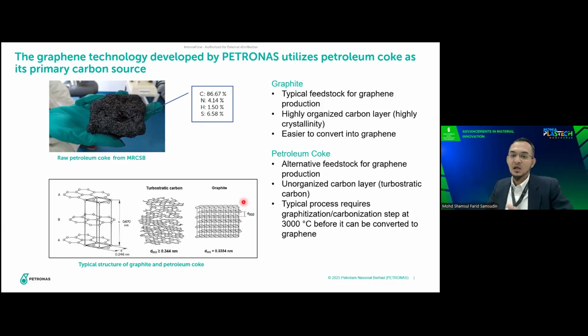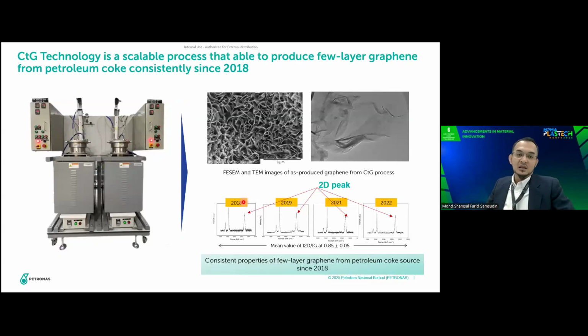But in our case, by using our technology, we're able to convert this petroleum coke at a much lower temperature, below 1,000 degrees Celsius. And this is how our reactor looks. We consider it a modular reactor, with a capacity of around 100 grams of graphene per reactor, and we have consistently produced this graphene since 2018.